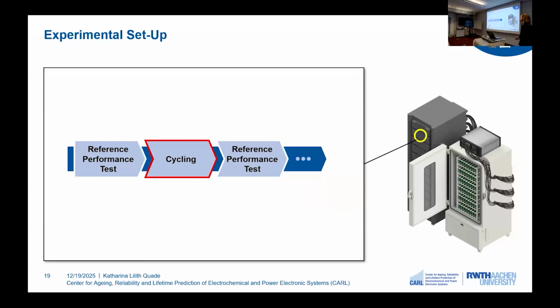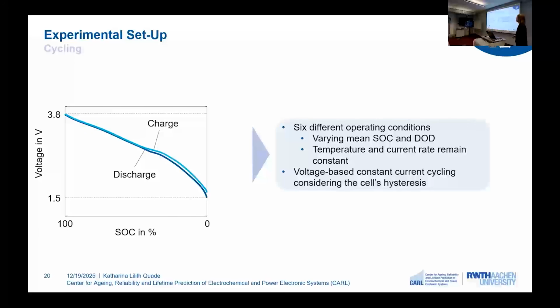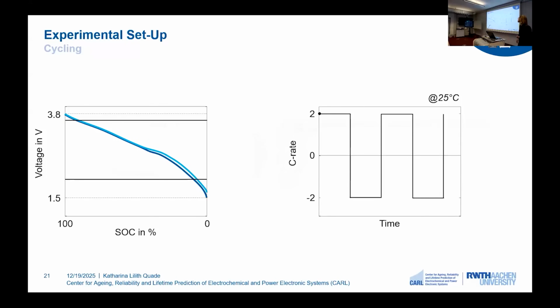Let's first have a look at the cycling conditions. Here on the left-hand side, you can see the characteristic voltage curve over SOC. In light blue, you can see the charge curve, and in dark blue, you can see the discharge curve. And we now vary the operation by varying the voltage operation range. So we have 6 different operating conditions where we vary the mean SOC and also the DOD, whereas we keep temperature and also the current rate constant. And we do voltage-based constant current cycling considering the cell's hysteresis, hence the difference between the charge and the discharge curve.